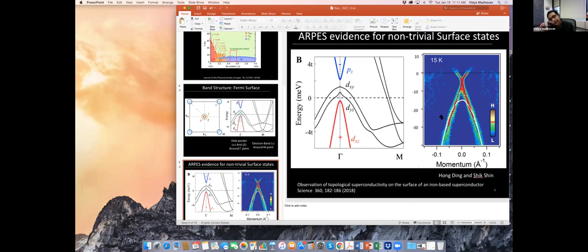I think that given all the beautiful work done by Hongding, Hongjun Gao, and Hanaguri, showing that these Majorana bound states exist inside the vortex cores in these compounds, you might think of it as indirect evidence. But I think that without a topological surface state, that would not happen. So just working backwards, you have Majorana bound states. That requires a topological surface state, which in turn requires band inversion at an odd number of points inside the Brillouin zone. So that's my answer.